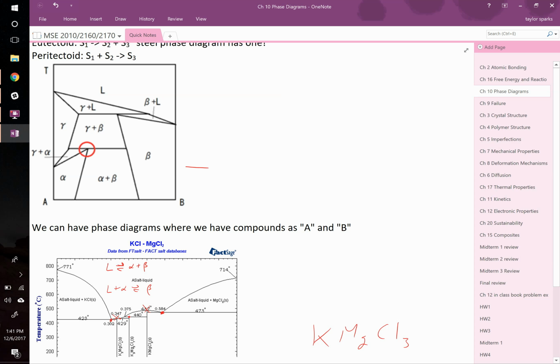And on alloys, if you do this low temperature anneal, and you choose a temperature where you specifically cross one of these phase boundary lines, it won't segregate all the way to the grain boundaries, which maybe doesn't give you the hardening you want. What you want instead is a bunch of tiny little precipitates all through your grain, because every one of those little precipitates will pin your dislocations. If you pin your dislocations, you get harder and stronger.